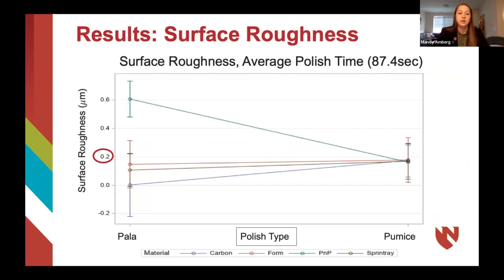Now I'm going to discuss our results. This graph summarizes our findings on surface roughness at the average polish time. The higher the surface roughness value, the more rough the sample was, and the lower numbers correspond to a smoother surface. Looking to the left of the graph at the top green line, we can see that there was